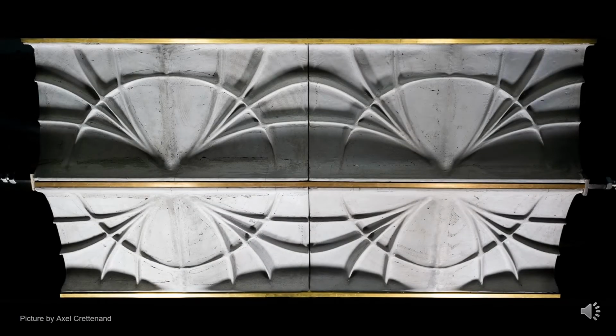The final prototype included 2 1 square meter slab modules that were made using the same 3D printed formwork. The 2 parts were assembled using a single post-tensioning tendon, and the upstand ribs were monolithically connected with a concrete mortar cast in place. The interface between concrete parts can have a perfect alignment of the articulations due to the precision of 3D printing.